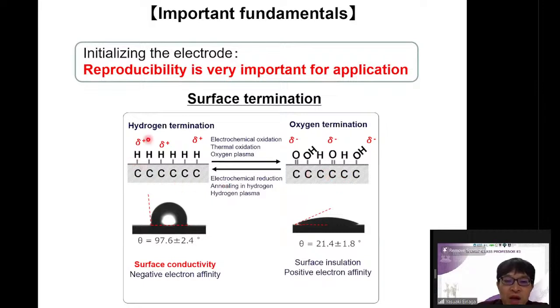So as grown, after the plasma preparation, the boron-doped diamond shows the hydrogen termination like this. However, the surface can be oxidized like this. We call this surface oxygen termination. This hydrogen termination and oxygen termination is very easy to control, but in other words, the sensitivity is also different. So we should control the surface very, very carefully. For example, if the surface is different, the signal of the current will be different. This is a problem for the application.